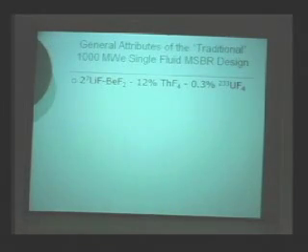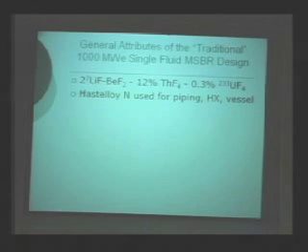The salt composition uses enriched lithium and beryllium fluoride — called FLiBe — mixed with thorium and the fissile U-233 created from the thorium. We use a nickel alloy called Hastelloy-N for all the piping, heat exchangers, and outer vessel. It's a hot operation: 565°C inlet, 700°C outlet. That gives us pretty high efficiencies — about 44% the old way on steam, and up to about 48% efficiency with the gas cycles.